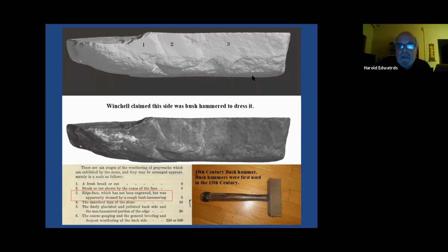built in the late Middle Ages. So they took rock from the same quarries, bush hammered the surfaces, and lo and behold, after a decade or two, they were falling apart. So if you're doing restoration work, don't use a bush hammer.